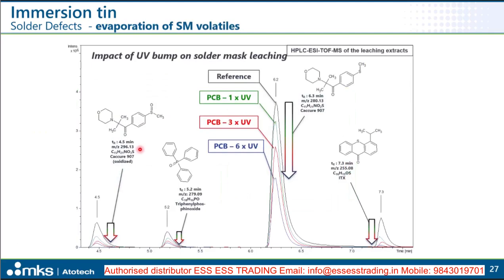Beside that, what was also tested, for example, was the effect of the solder resist on the de-wetting defects in immersion tin. For example, we did tests with different cured solder masks, having different curing conditions, and then checking if we can improve the performance of the immersion tin layer. And we also try to analyze the, let's say, leach out of the solder mask if the solder mask is not properly cured.